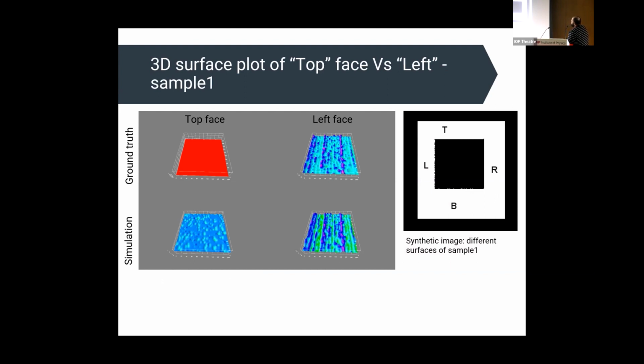So here I present the 3D surface plot of the top and the left face in sample 1. Just to remind you, the top face has very little surface roughness, and the left face as well as the bottom face have much more surface roughness. And that can actually be seen in here. That's our ground truth, that's the synthetic images, and that's the simulation here.